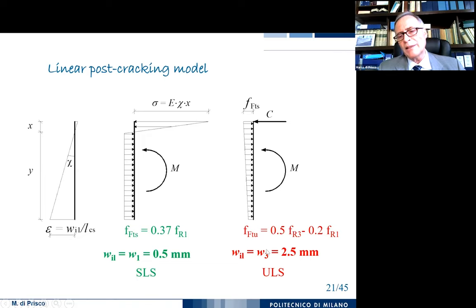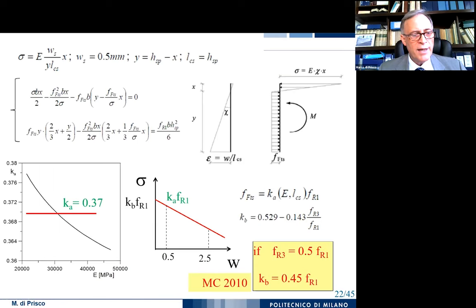And when we look at the ultimate limit state, we apply only the rotational equilibrium, and we can immediately obtain the relationship between FFTU and the two flexural strengths, FR3 and FR1, identified by means of EN 14651. Okay, this approach can be explained by these two equations and this assumption. What is very important to see is that, depending on the elastic modulus and also on the compressive strength, you could have different values of the factor which correlates the flexural strength FR1 to the value KA, which corresponds essentially to the value for the crack mouth opening displacement of 0.5, what we name FFTS. But if you look at the variations, they are not so huge. So usually we accept a constant value, which is equal to 0.37.